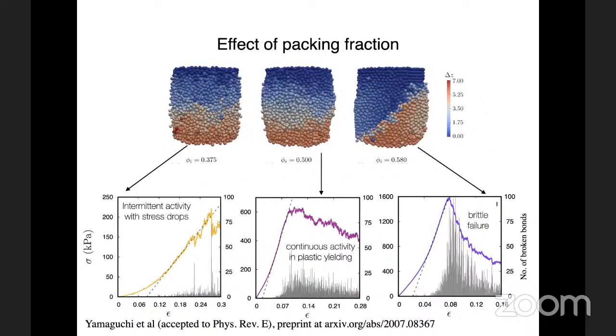And if you look at the stress strain curves of those, you can see the very different modes of failure. At the high volume fractions, like the experiments, we have a brittle failure. If you look at the activity in gray, you find low activity until just before the failure point. You have a critical burst of activity when it fails, and the stress goes down rapidly past that point.